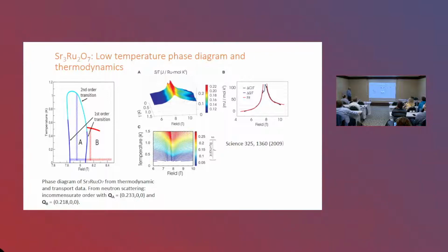Moreover, the more intriguing findings were a bit earlier, that in that ordered state where we have the SDW, where at the borders we have the metamagnetism, entropy is higher. Completely counterintuitive, because you expect in an ordered phase entropy to go down because you gap parts of the Fermi surface.